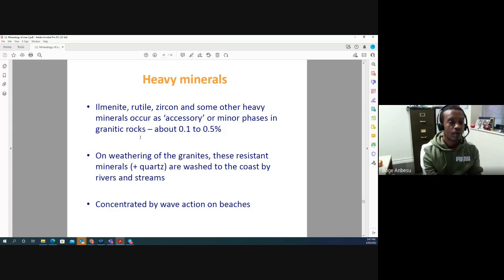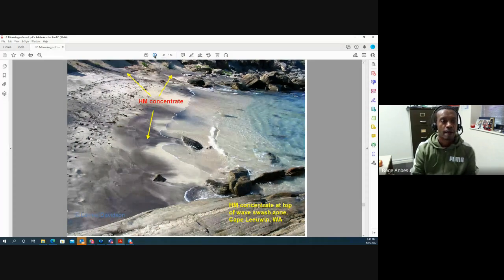So you could use magnetic separation to separate out the ilmenite first, then come back and use electrostatic separation to remove the rutile, and then you have zircon as the third concentrate. All of this can be shipped and sold individually, and therefore you can have different sources of income from the different concentrates that you're producing.